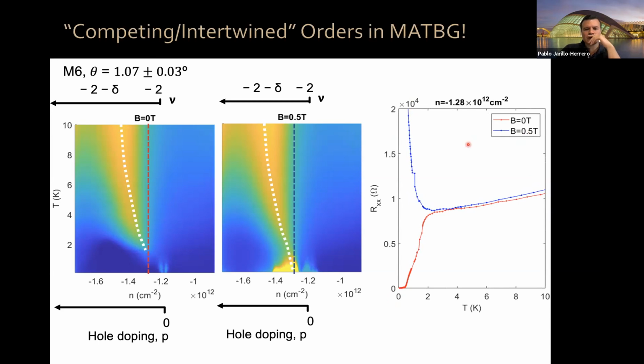So this is something that we have observed, and of course, we can do these measurements that I just showed you at 2 different magnetic fields. We can do them continuously as a function of magnetic field. So this is a plot of the critical temperature versus doping, and I have superimposed here different perpendicular magnetic fields so that you can see that this original dome, which exhibits a depletion there, eventually separates into 2 domes, and then only the last remaining dome, the strongest, remains up to a few hundred millitesla.